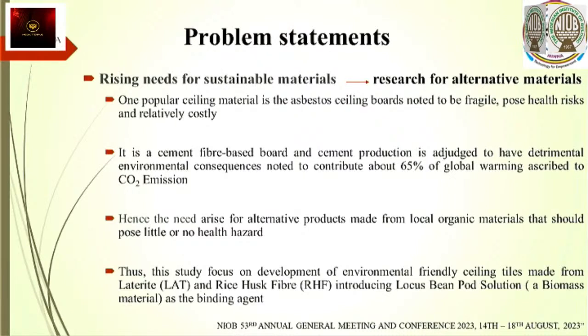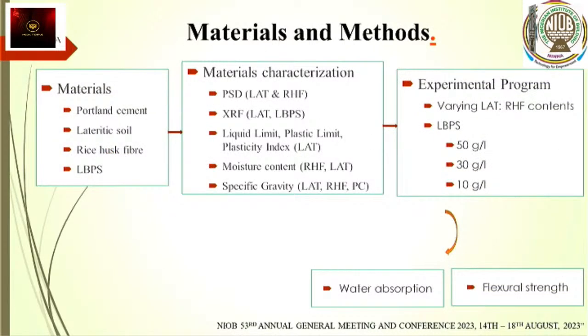We looked at material characterization. That's to look at what are the characteristics of these materials. We carried out particle size distribution on laterite and the rice husk fiber. We carried out XRF, that's X-ray fluorescence, on laterite and the locust bean pod solution. We carried out liquid limit, plastic limit, and plastic index test on the laterite, and we carried out moisture content on the RHF and the laterite, and also the specific gravity of the three materials, laterite, RHF, and Portland cement, were looked at.